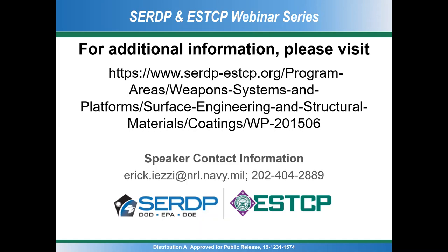Great. And in closing, can you please summarize the next steps in this really interesting work, Eric? So the next steps are, as I mentioned, we're continuing to paint aircraft. Every 6 months, we will collect metrics from the different aircraft that were painted with the polysiloxane top coat. That'll include dry film thickness measurements, color and gloss. We'll check for any sorts of cracking or delamination and so on. And we plan to do that hopefully out to a 2-year period so that we've collected sufficient data. And then compare that to what we see with the polyurethane top coats that are found on aircraft.